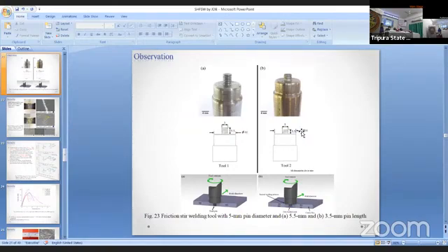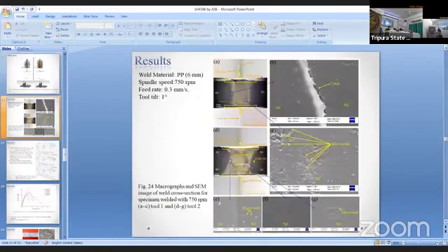What happened initially with the first pass is that, throughout the cross section, the maximum of the material height could deform, and subsequently, when we went for the double pass, a better weld quality could be obtained in comparison to the conventional tool. However, here also cracks have been observed, micro voids were present, and a turbulent flow of the material was also observed. So that's why we again thought that this is not yet ideal for welding polypropylene material. Again, we can make it better.